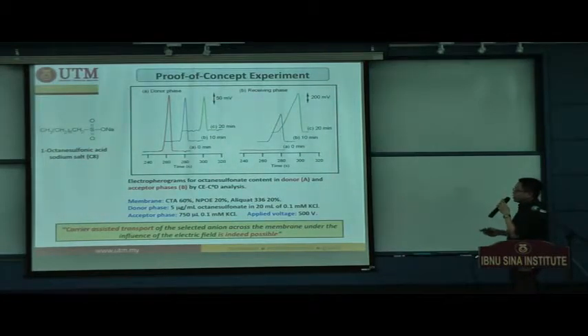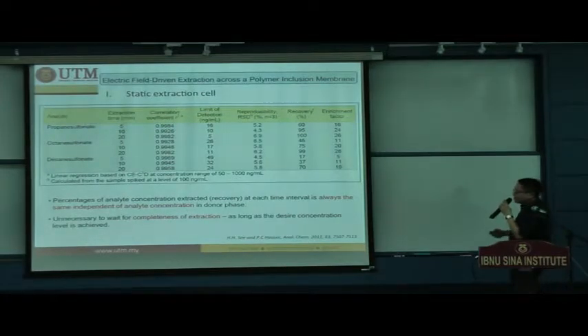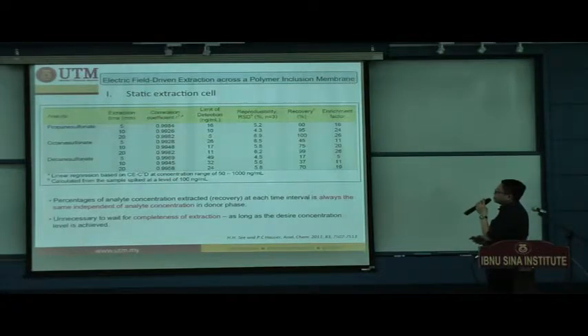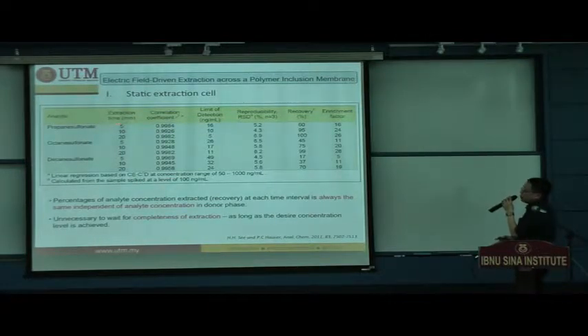So we are very excited. I remember I repeated this experiment more than 50 times just to make sure that everything was working before we proceeded to the other optimizations. And after the optimization process, this is the overall result, showing 3 different kinds of alkyl sulfonic acids spiked in the samples. We performed the extractions at 3 different time intervals: 5, 10, and 20 minutes. And this is the limit of detection for each of the extractions.